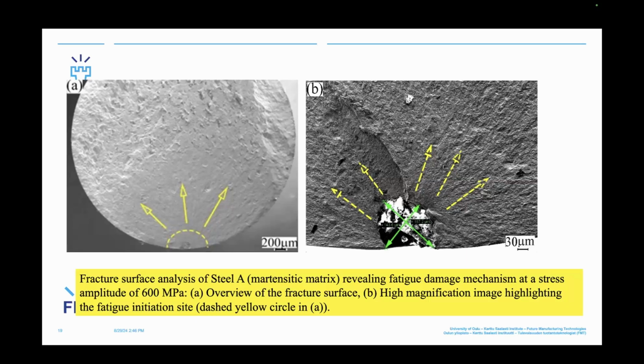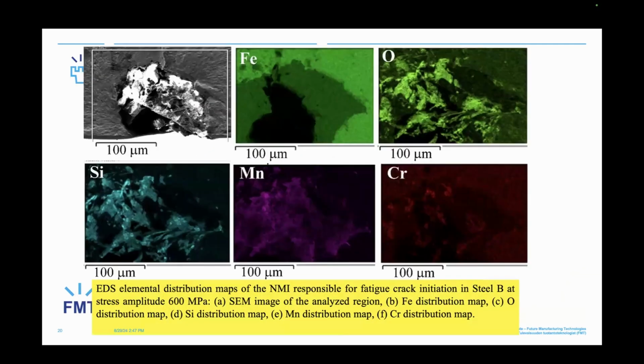Okay. Now we come to the fracture analysis. We can see here the fracture initiation region, here crack propagation, and this overloaded region. At high magnification, we found a non-metallic inclusion, a big inclusion with dimension 150, and this makes the fatigue initiation region. Unfortunately, this particle is on the surface, and we know we have higher stress concentration on the surface.